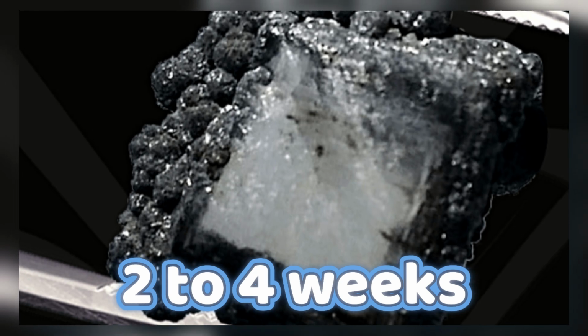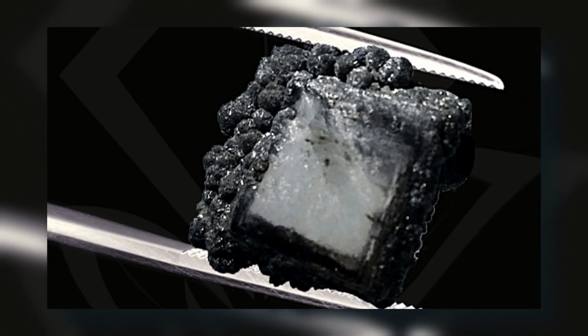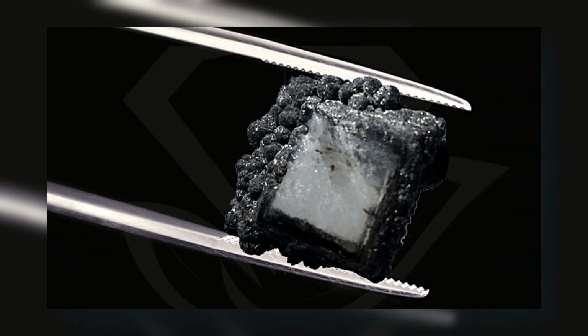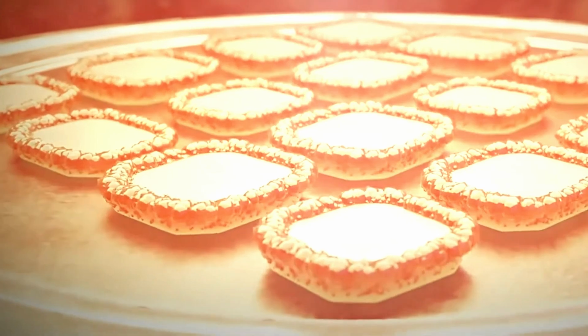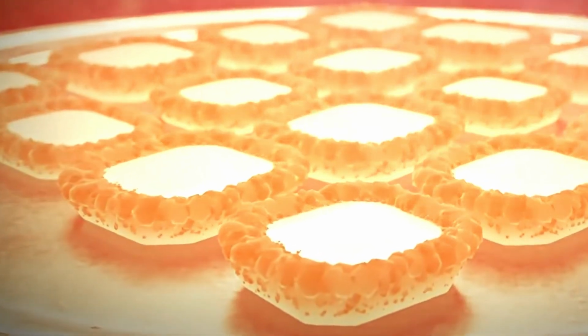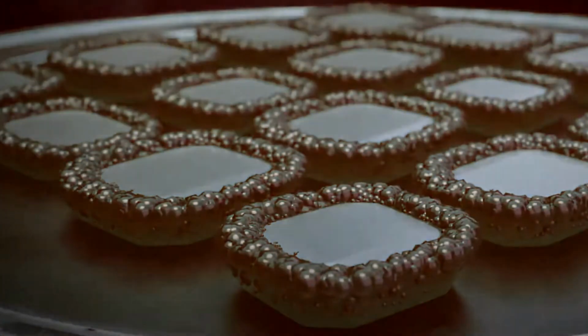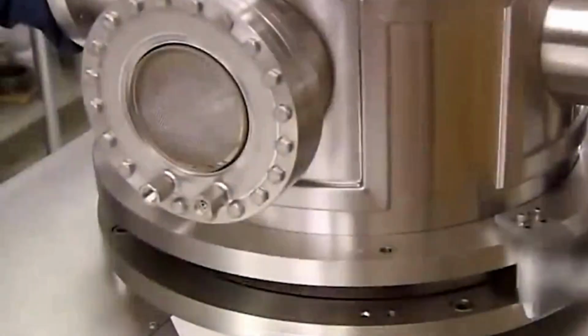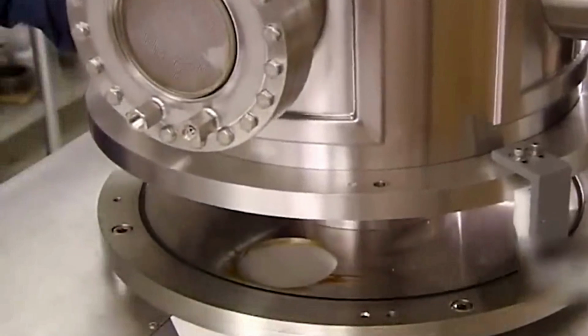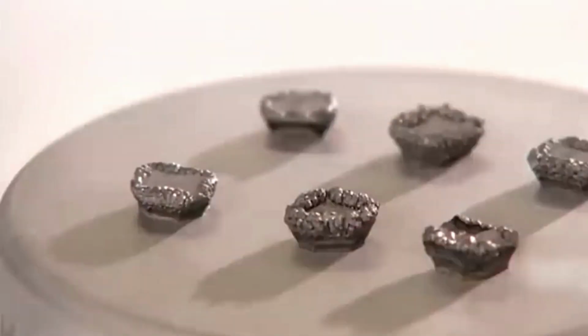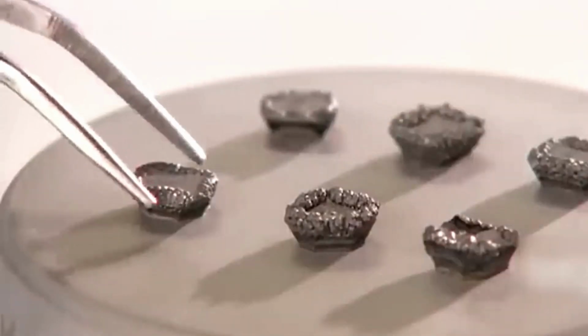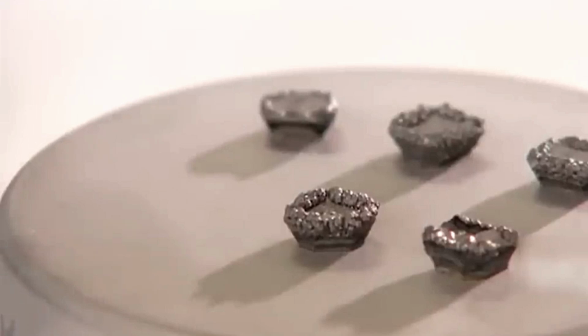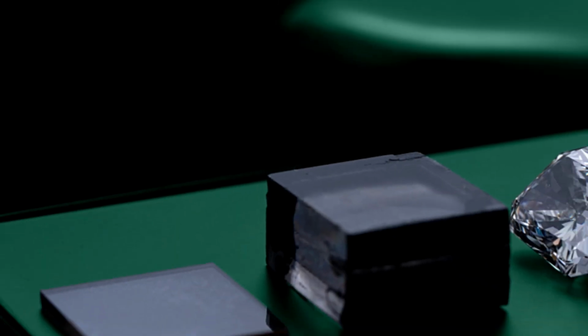Over 2 to 4 weeks, layer by layer, the crystal grows, sometimes reaching several carats. The process is tightly controlled to achieve 99% carbon purity, with trace elements like nitrogen, which can yellow a diamond, or boron, which can tint it blue, minimized through precise gas mixtures and chamber conditions. Advanced sensors monitor temperature, pressure, and gas flow in real time, ensuring the crystal forms without defects that could cloud its clarity.